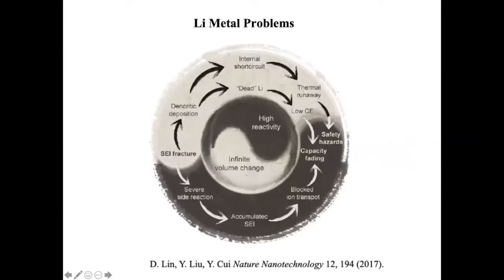So in this perspective and review paper, we highlight the central part of that. Lithium metal has its problem: high chemical reactivity, as well as relatively infinite volume change, right? This volume change goes from an empty state during stripping to a filled state during deposition. The relative change is infinite. You need to overcome the rest of the surrounding problems you observe. So we really need to overcome this fundamental, I'll say, the root cause in the center right there. That has been guiding my whole research group. I believe many scientists in the research field will agree with me. This is a very important root cause that we need to overcome.